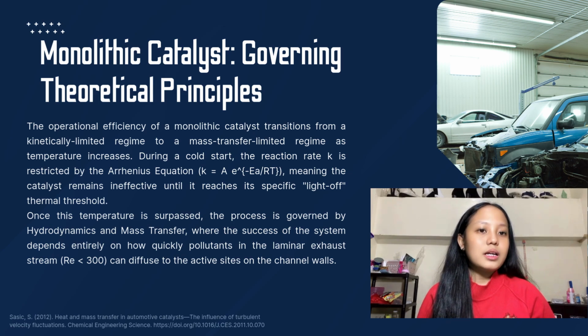However, physics can only take us so far. We need the chemistry to wake up. During a cold start, the system is kinetically limited, following the Arrhenius equation. The reaction rate k stays low until the engine hits the light-off temperature. But once the thermal threshold is crossed, the activity surges. At this point, the chemistry is so fast that the only bottleneck left is physics. The system becomes mass transfer limited, meaning its success depends entirely on how quickly those gases can physically reach the active sites on the channel walls. From a cold ignition to high-speed cruising, the monolith is a masterclass in the interplay between transport and transformation.